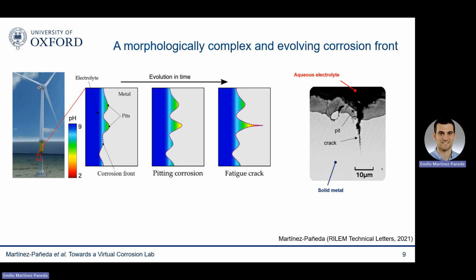In corrosion, defects are not stationary. The interface between the electrolyte and the metal is continuously evolving. You get pitting, a pit to crack transition, so you need to capture this. And this is going to be closely linked to everything that I showed you in the previous slide. You can see it very nicely here with this example of corrosion fatigue in offshore wind turbines. And corrosion fatigue is what governs the lifetime of these offshore wind turbines, which is only 25 years.